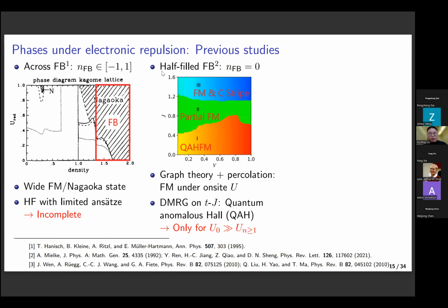Secondly, people have paid particular attention to the half-filled flatband. For example, back in 1992, Mielke applied the combination of graph theory and percolation theory to claim that ferromagnetism is a mathematically rigorous ground state under the on-site repulsion. And more recently, in 2021, D.N. Sheng's group has done a DMRG on a t-J model, and they found that if we add an extended repulsion, there could be a quantum anomalous Hall ferromagnet and also some ferromagnetic charge spread.